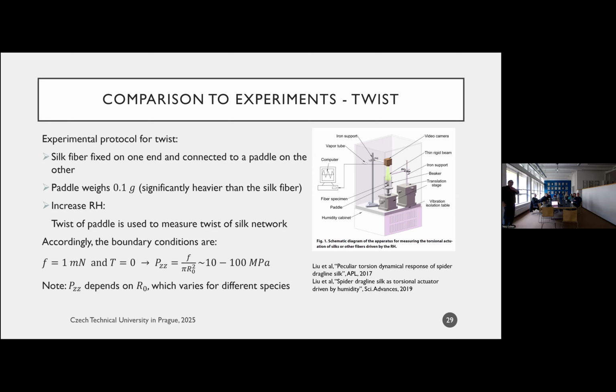What they've done is they said, I know the fiber is extremely small. It has a very small radius of micrometers. I'm not going to be able to see twist, right? I don't have the scale to see the twist. And so what they've done is they said, we'll take the fiber, we'll hang a paddle at the bottom, so that there was a paddle that weighs about 0.1 grams. It's much heavier than the fiber. And what we're going to do is increase relative humidity, and measure how much the paddle twists, right? And based off of the twist of the paddle, we'll be able to say how much the fiber twisted. It's a pretty clever setup.